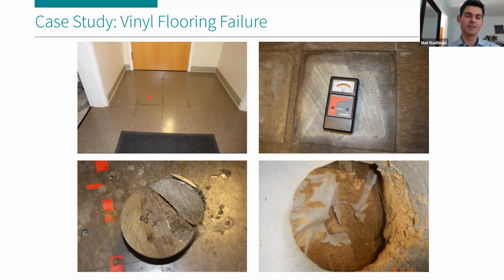localized but widespread failures of vinyl flooring, which, as you can see, manifested in the form of blistering and bubbling along, in this particular case, vinyl composition tile edges. There were other areas with sheet vinyl flooring that exhibited similar issues. Upon removal of the flooring, we determined extremely high moisture content in the underlying concrete slab, and evidence of re-emulsification of the adhesive around the perimeter of the tile, as well as evidence of mineral deposits accumulating on the concrete surface.